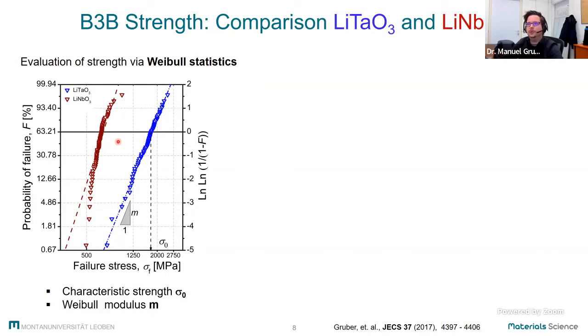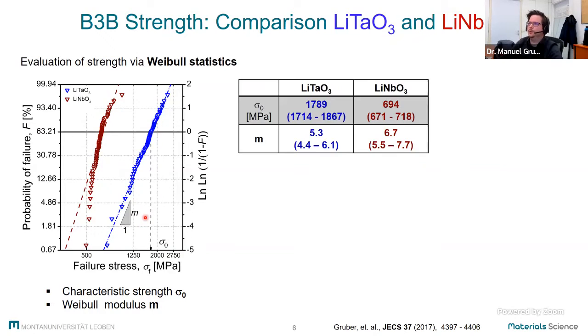We see here a Weibull plot where the probability of failure is plotted versus the failure stress. Two important values are the characteristic strength, so the stress at which we have a probability of failure of 63%. And the second important parameter is the Weibull modulus, so basically the slope of this fitted curve. And this shows the scatter of data. So a high m means that we have a low scatter of data, and a low m, as we observed here, means that we have a high scattering in strength values.